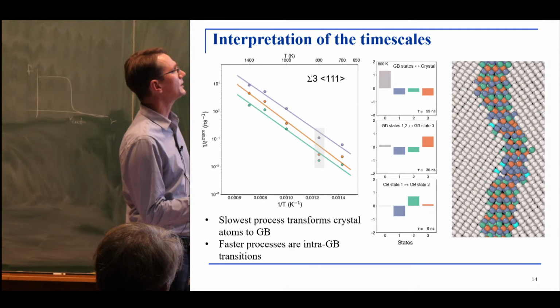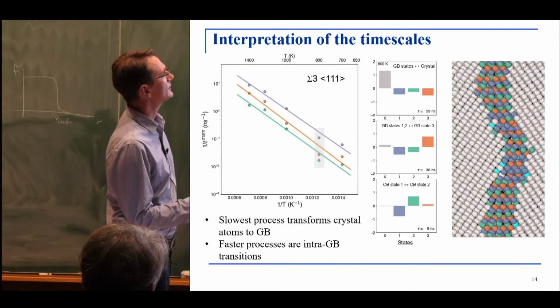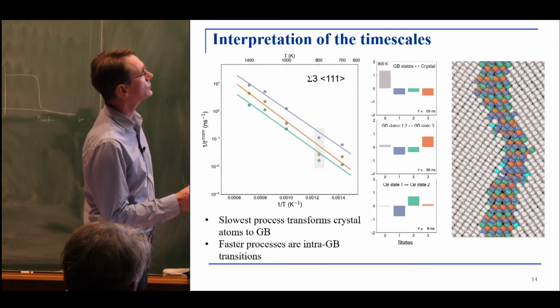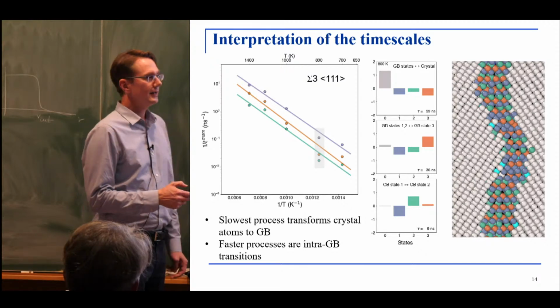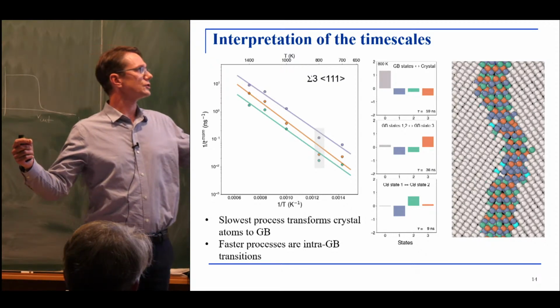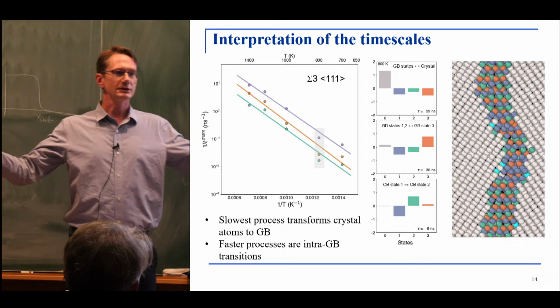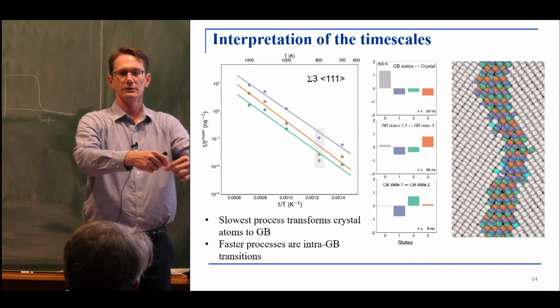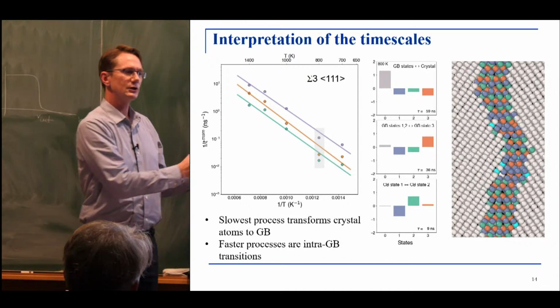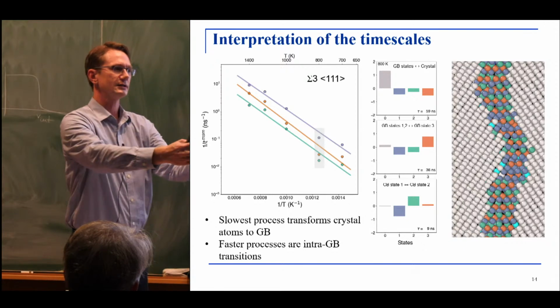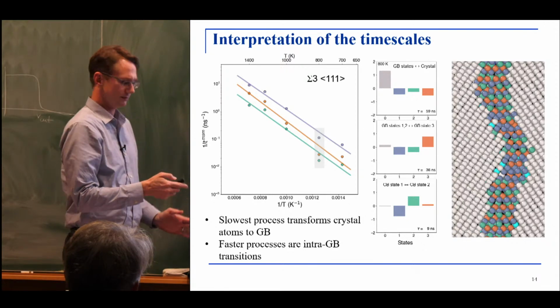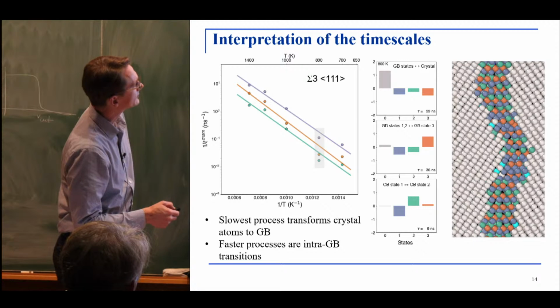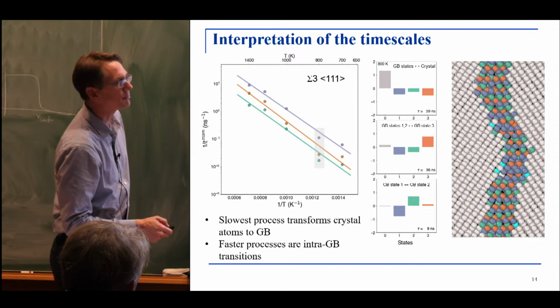So this is telling you that there is a transition from state 0 into the other 3 states. And this is simply the conversion of an atom from the crystal state into the grain boundary state. So this should ultimately correspond to the overall translation of the interface. And then there are faster processes that correspond to intra-boundary transitions.